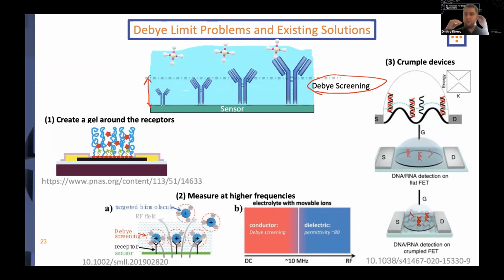Your normal blood or normal cell line would have a Debye layer of approximately 1 nanometer. So if your biorecognition element is below that 1 nanometer, which is rare, you're safe. Your reaction would work and you'll record it very nicely. But if your recognition element is way above the Debye layer, whatever charge is attaching here, you'll most probably not record it. So this is a problem, and there have been a few approaches to it.